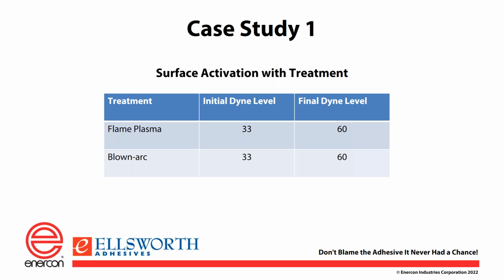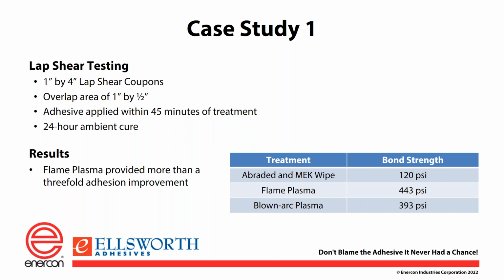The initial dyne level for both was 33, and you can see that we got the same 60 after treatment. That's a nice delta there. That's a good repeatable number that you can use. And then we did the pull testing on that, 1 inch by 4 inch lap shear coupons, and they were pulled apart within 45 minutes of treatment. You can see the untreated sample had 120 psi of strength, and in this case, it looks like the flame plasma did better on the pull test at 443, and the blown arc still did much better than the 120, at 393. So again, this is a case study showing the difference of just what can happen if you treat that material. You're increasing the energy on the surface, and you're going to get a better bond.